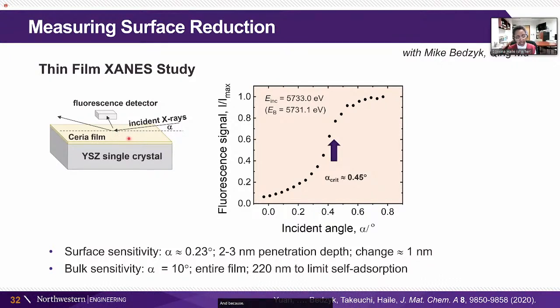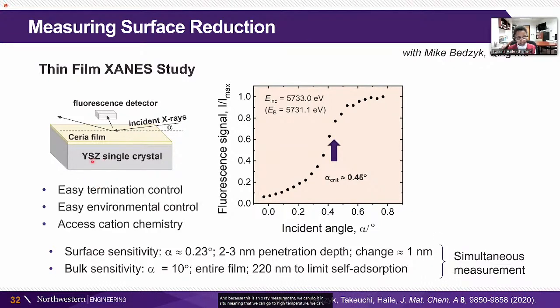And because this is an X-ray measurement, we can do it in situ, meaning that we can go to high temperature, we can control the environment, introduce oxygen, introduce hydrogen to make it more reducing, and we can also do fluorescence at the same time so that we can measure the cation chemistry, and we can get the single crystals in different orientations so that when we grow our ceria film on top, we get different terminations of the ceria film.